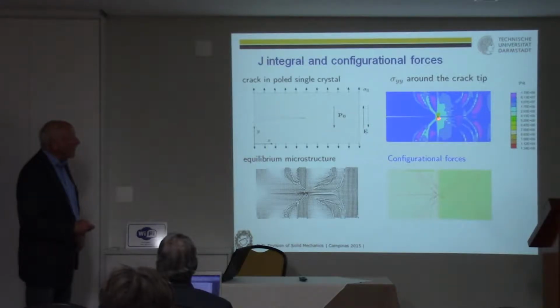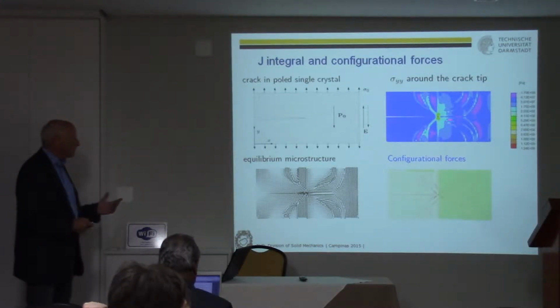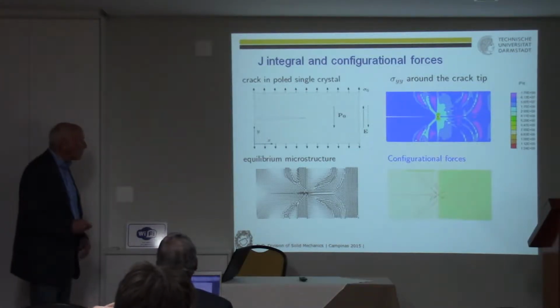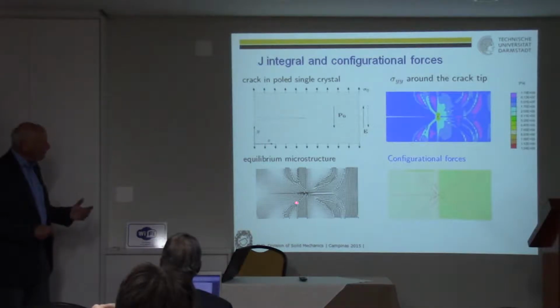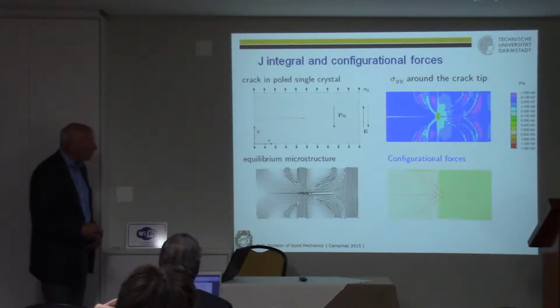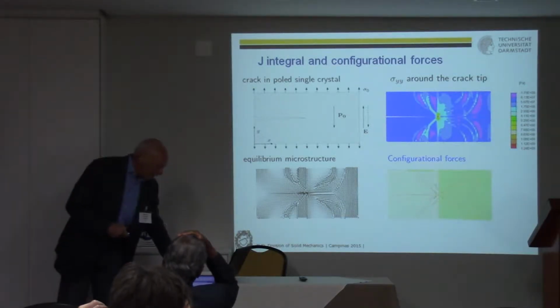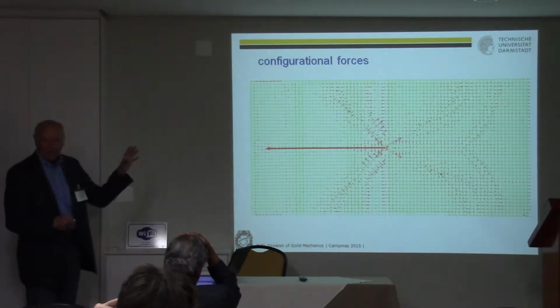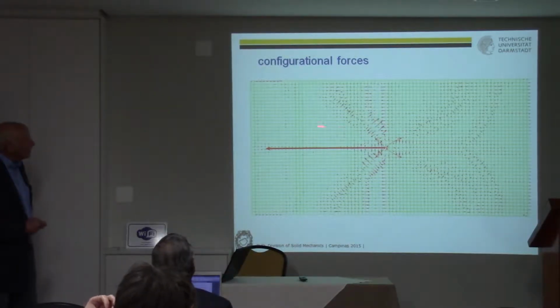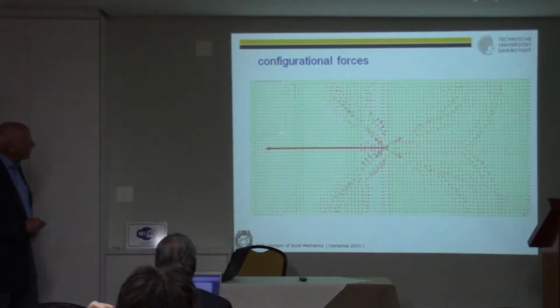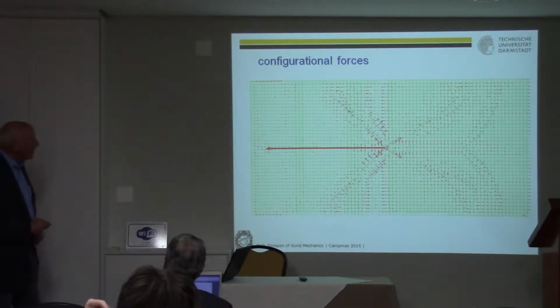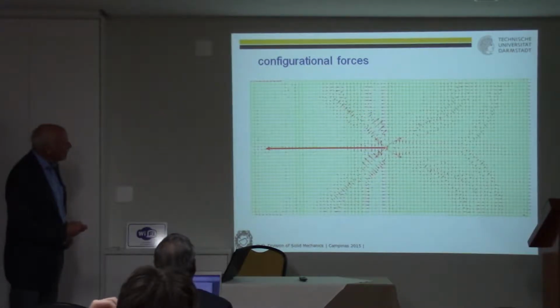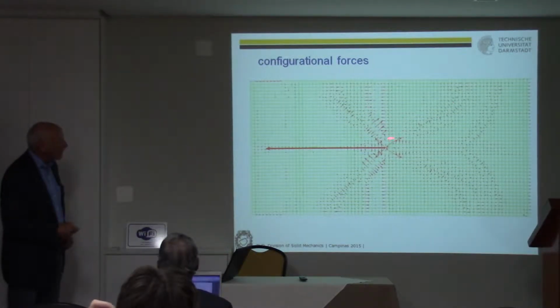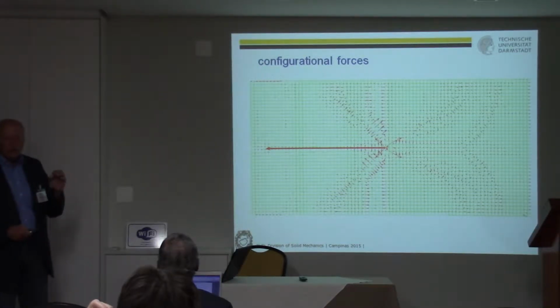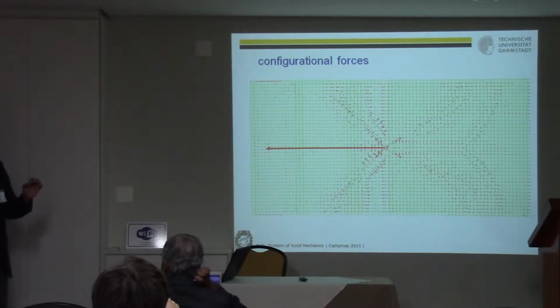This is what you get, for instance, the stress distribution, strain distribution, and so on. The polarization field around the crack, and here are the configuration forces. To see it a little bit better, I have magnified this picture, and you see here are some spurious forces. This is numerical dirt. But what you see here, these are really acting forces on the domain walls. And this really big force, this is the driving force acting at the crack tip.